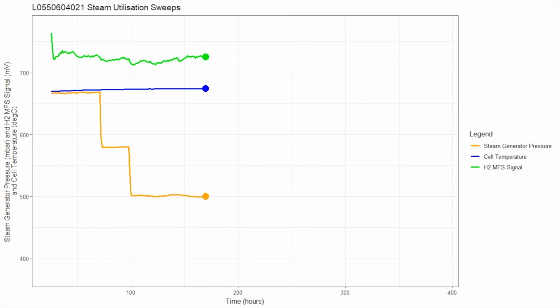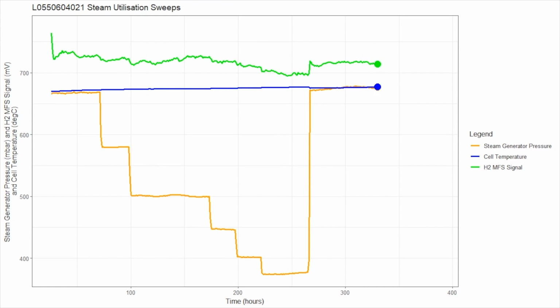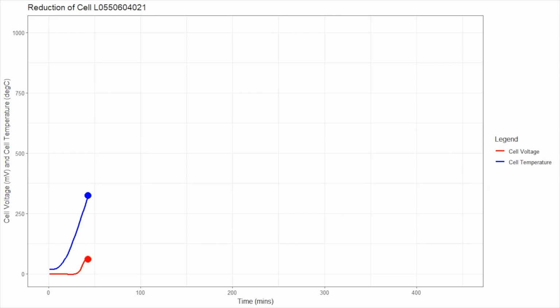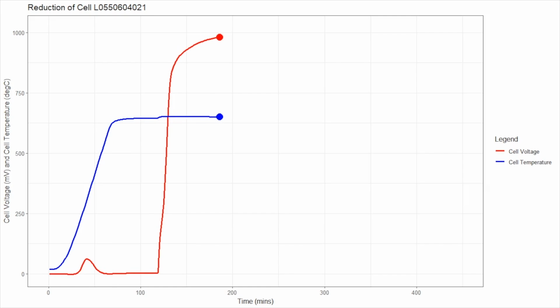Prior to the addition of catalysts, our cells showed energy consumption of about 45 kilowatt hours per kilogram of hydrogen. Initial cell tests with catalysts show improved performance in both energy and degradation metrics.